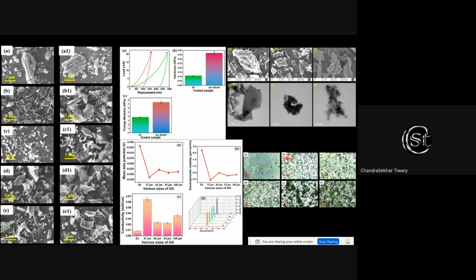Now, let's look at some of the processing parameters which we optimized. We did different temperatures and times, and as you increase the temperature, we see a higher surface area, the flakes get exfoliated and so on. We also compared the coating hardness and Young's modulus to pristine epoxy. The transmission electron microscope shows that if you tune the parameters, we can make very thin flakes and also smaller size flakes during the process.